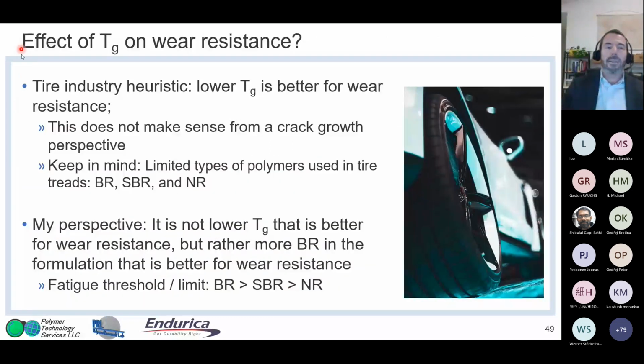But what about the Tg effect? There is this tire industry heuristic: lower Tg is better for wear resistance. Based on dissipation in front of the crack tip, this never made sense to me from a crack growth perspective. If anything, higher Tg should be better.